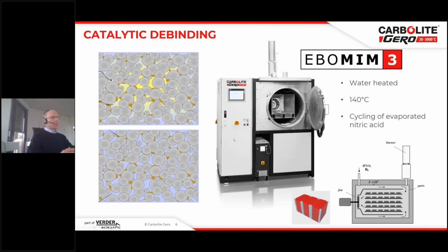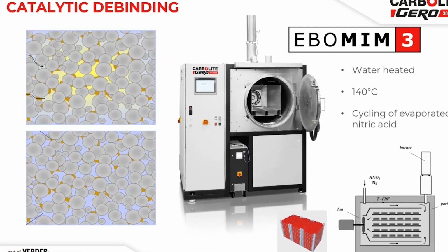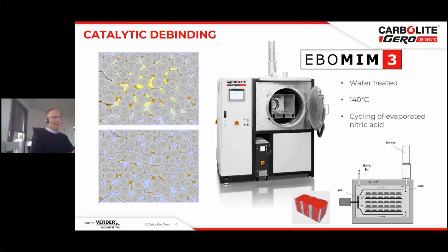So now I go to the indirect method, and I told you before, the first thing in the indirect methods is the debinding. And the most important thing is we talk about two different kinds of binders. We have the main binder, and the main binder is shown here with the yellow color between the powder particles. That is the main binder, and the main binder you get rid of by means of either a thermal debinding or a solvent debinding, or the example we show in this case is a catalytic debinding.